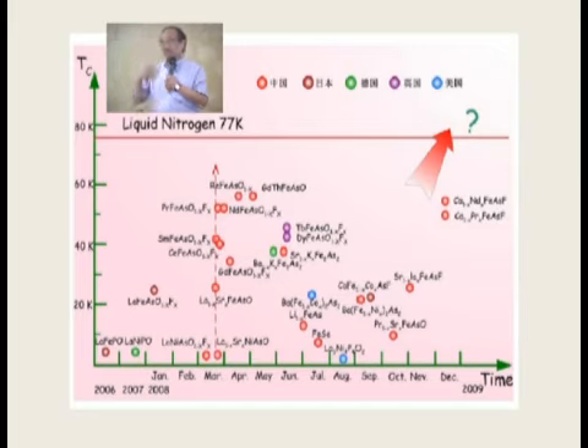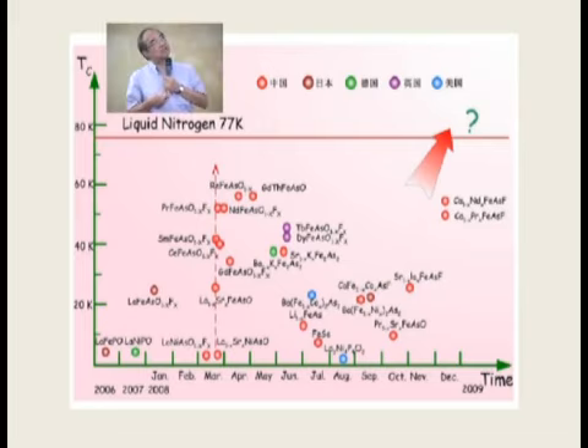That's why you can tell why superconductivity is so important, because of the excitement created every time you find something. By 2009, it was already shown that the TC can be as high as 60 Kelvin. So people started to think about whether we can break the barrier in this system. Unfortunately, so far there's still no such sign.